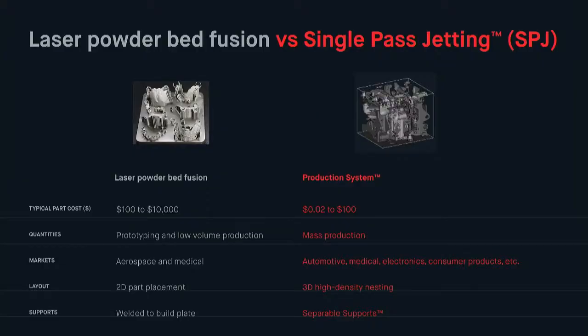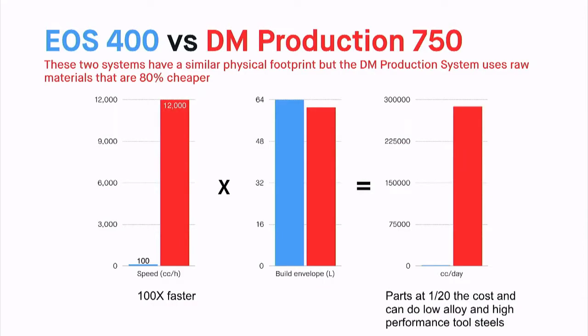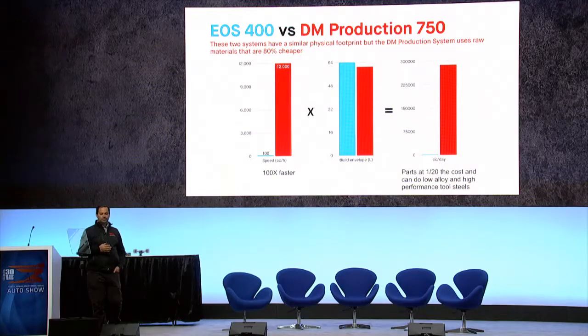And again, when you compare it to powder bed fusion, you end up with parts that are dramatically less expensive than conventional systems. For example, an EOS 400, there are trade-offs to our technology, and I'm happy to talk about it, but if you compare an EOS 400, which is the fastest machine from EOS, they're about 100 cubic centimeters per hour. Our production 750 machine is 12 liters an hour. Similar build envelope, dramatically higher productivity. And they are not able to do things like D2 tool steels or 4140 or a lot of the materials that are actually used in industry.